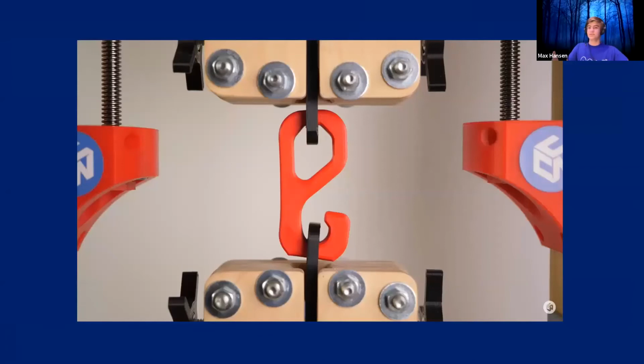You can see, sorry, with this tensile strength tester that he has made, he's begun to test some 3D printed parts. He designed this hook out of Prusament PLA, the filament he's going to be testing. And as you can see, this is not the same as the dog bone style thing that the industry testers use. And actually, a really important thing about this is it has one force going kind of that direction and then one force going up. So it's testing kind of two strengths at once, per se. And so he can put these hooks into the machine and then begin to test them and see what happens.